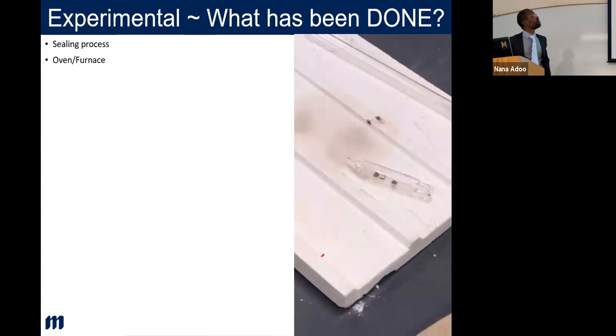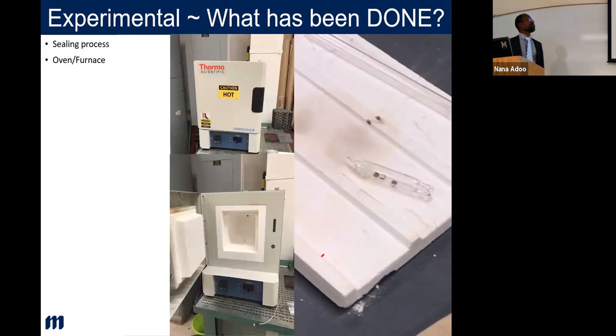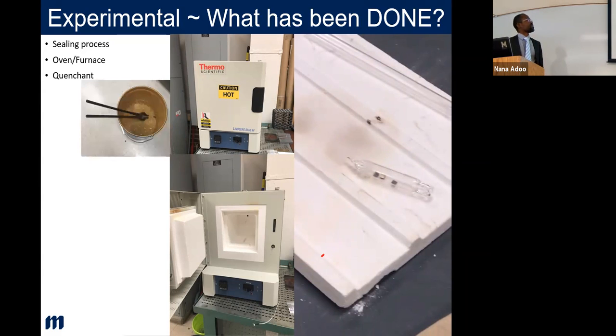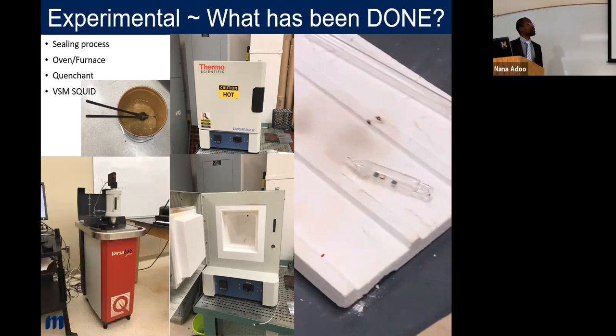So that was the sealing process, and the oven I have used over the years is this one. You have it open there. It goes up to 1,150 degrees. And this is the quenching, which was done in an ice water cooled bucket. Once it's sealed and heat processed, we get it ready for a SQUID measurement. This is the SQUID which I used. It's not in the school here, it's at SDSU, so I had to go to Brookings to take those measurements.